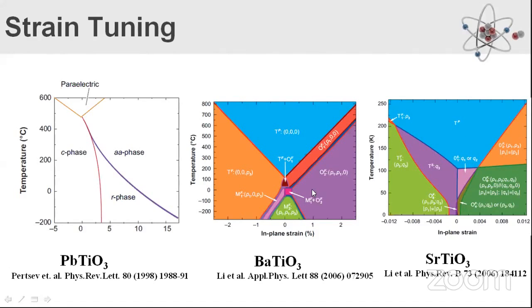But if you apply tensile stress, it changes to orthorhombic, and then there is a combination of monoclinic and orthorhombic. So you can play a huge part by changing the in-plane strain. By changing the substrate strain, you can have a tetragonal structure, or an orthorhombic structure, or even a monoclinic structure.